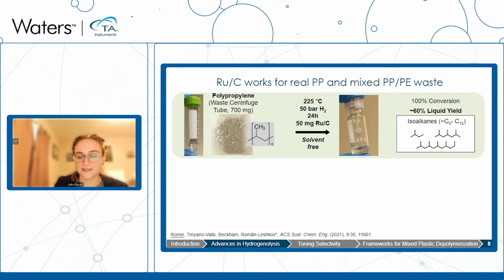And in fact, this ruthenium on carbon catalyst also works for deconstructing polypropylene, mixed polyethylene and polypropylene waste, and realistic feedstocks. So here we went around the lab and actually found this polypropylene centrifuge tube, cut it up into little pieces, added it to our reactor along with our catalyst and the hydrogen, and after 24 hours at 225 degrees C, again in the absence of solvent, we can recover this 60% liquid yield of this nice liquid product that's comprised of isoalkanes, so branched alkanes, with carbon numbers from C5 to C15.